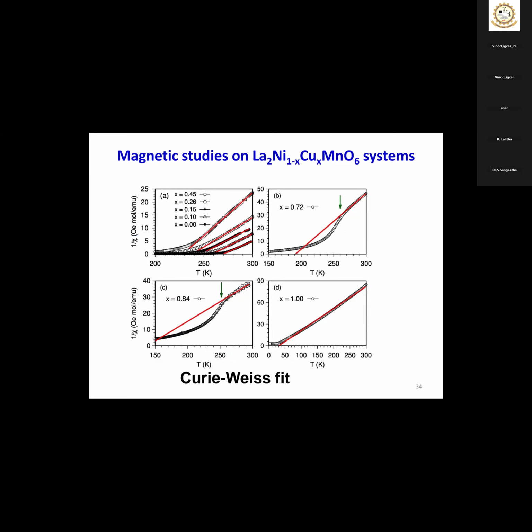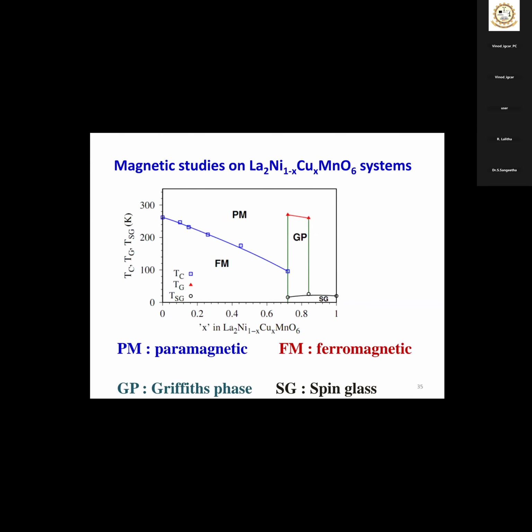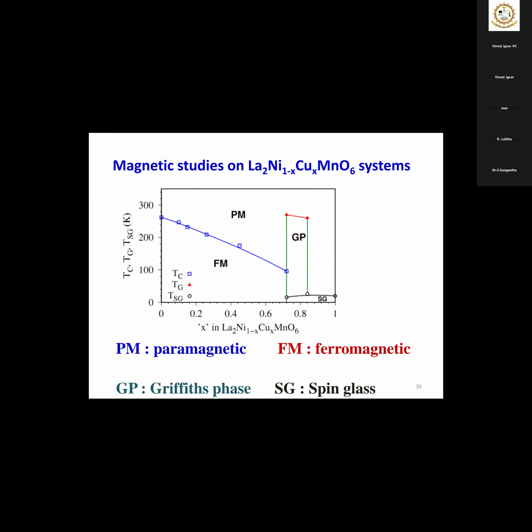Okay, so this is the Curie-Weiss fit analysis. This is also a little technical. The interesting thing is for the lower copper content, it is following the ferromagnetic trend. As you increase the copper content, there is a deviation from the Curie-Weiss law. What it means is called a Griffiths phase, that I will explain later. And the end compound is spin glass. That also I will explain schematically and briefly.